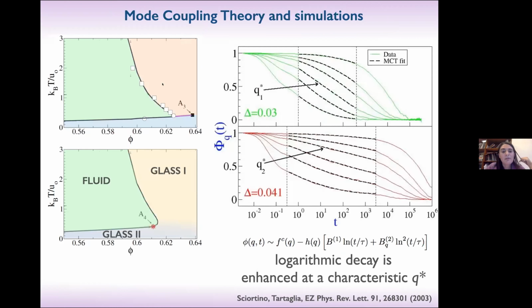So doing that, for the A3, which means that we are somewhere here in the phase diagram, at delta that is 3% of the diameter, that is a very, very narrow width that is possible in experiments, because in experiment, you remember, you have these polymers that are much, much smaller than the colloids. And so if you calculate the density correlator of this simulation at different Q versus time, you find this behavior. And this is the predicted asymptotic behavior from the theory: you have a logarithmic term plus a logarithmic term squared and so on. But the coefficient of this squared logarithm depends on Q.